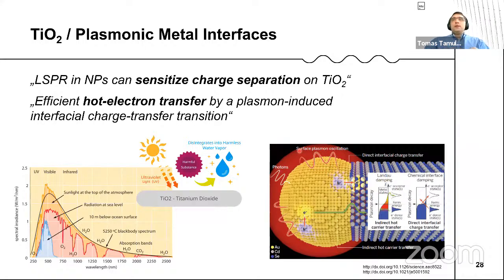We also had an idea that we can combine plasmonic nanoparticles with some interfaces with TiO2. And this material is known as good for cleaning the water and inducing catalysis, but it works only well for the UV part of the spectrum, and we know that the sun is shining a broad spectrum. The metallic nanostructures here can play a role because they can absorb light in the visible, and having this charge separation and transfer to TiO2, we can sensitize this reaction here.